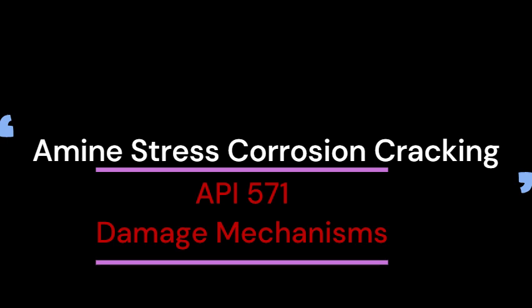Okay, so let's start at the beginning. What is Amine SCC exactly? Okay, simply put, it's when steel cracks, specifically carbon steel or low alloy steels. And it happens because of two things acting together: tensile stress, like a pulling force, and contact with a specific liquid, an aqueous alkanolamine solution. That's the stuff used to clean up the gas streams, right? The amine treating. Exactly. It's the chemical workhorse for pulling out H2S, hydrogen sulfide, and CO2, carbon dioxide, out of gas and liquid hydrocarbon streams.